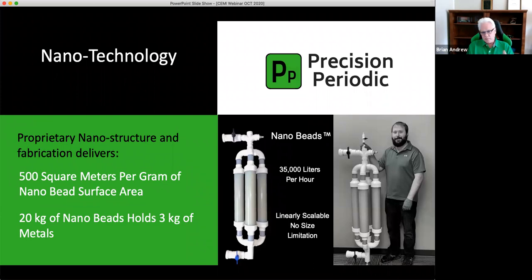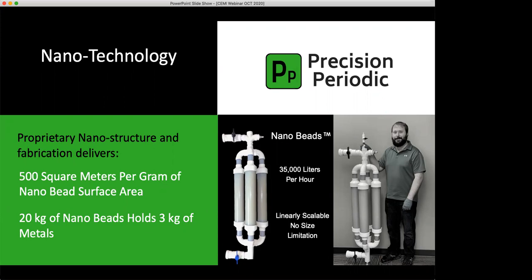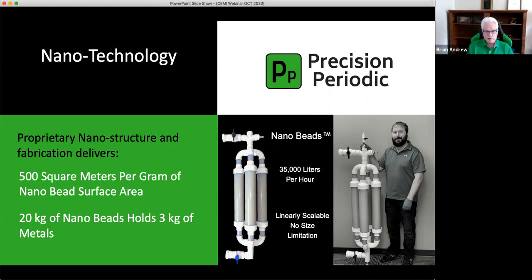So in the case of this filter we're showing here, we consider this our base unit. It's 20 kilograms of our filter material. It'll hold up to about 3 kilograms of metal of interest. So 3 kilograms of gold, silver and gold, copper, manganese, whatever it is we're extracting from the liquor. The physical area is actually quite small. So a plant that handles, say, 350 gallons a minute, for example, would only be the size of a small container. So again, the scale of this is remarkably small, but the performance is very high.